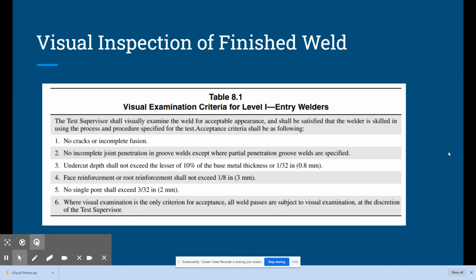So this is table 8.1, visual inspection criteria for Level 1. This is from the American Welding Society SENSE program. This is what I use to inspect the weld. So I'm going to run through this first, and then we'll show you a little video of an actual weld that we can inspect. So first of all, we're looking for any cracks at all. Any cracks, and again, this is prior to bending, after they finished welding it and it's cooled to room temperature. If there's any cracks on the surface of the welds at all, or any cracks that are visible, automatic fail for the bend test.